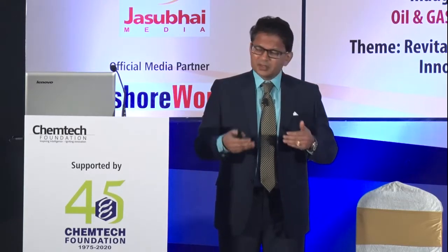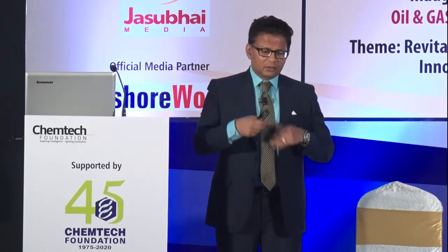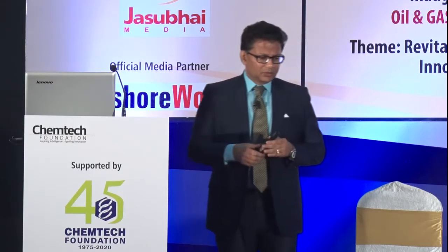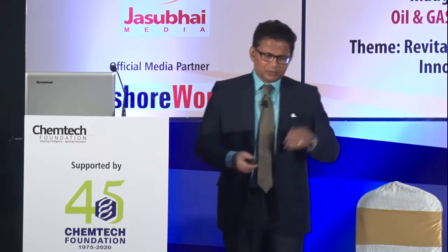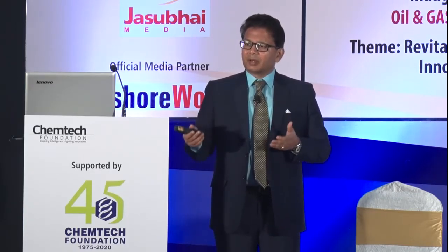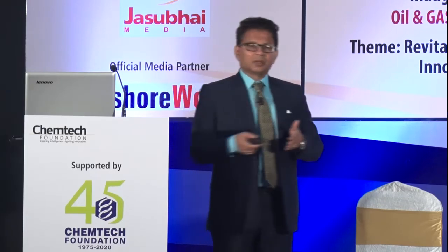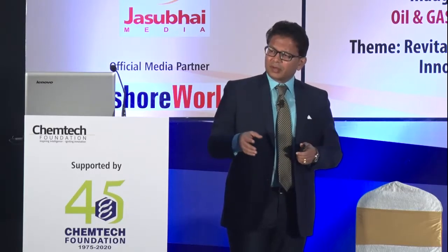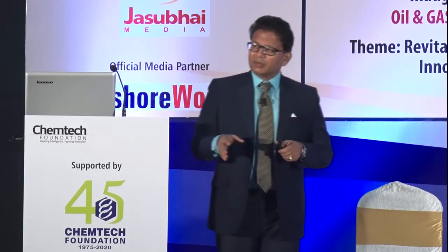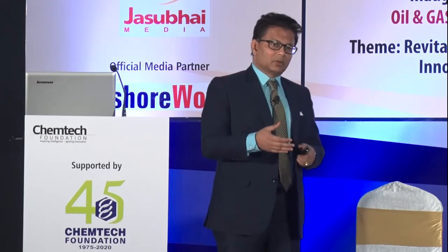So in summary, property-wise, why it works is because this is a chemical bonding of the coating with the substrate. It's just 0.1 millimeter, and then it goes through a process called vitrification, which gives that chemical bonding. And because of that chemical bonding and the very low porosity, corrosion resistance is very, very high. So now we're working with a refiner in India, one of the largest refiners in the world. They have a huge corrosion problem in their vinyl chloride monomer plant. They corrode even the Hastelloy C276 with the tungsten carbide coating every 6 months. It basically eats the whole assembly.